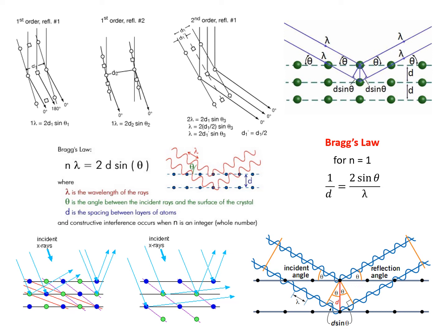over here somewhere. So the point about it is, if you follow through the path lengths, for example, in a Bragg-Brentano focusing condition, path lengths for waves coming from a source to a detector and scattering off atoms within a material, the path length is the same as if these were parallel waves coming in, a parallel plane wave coming in and being scattered.